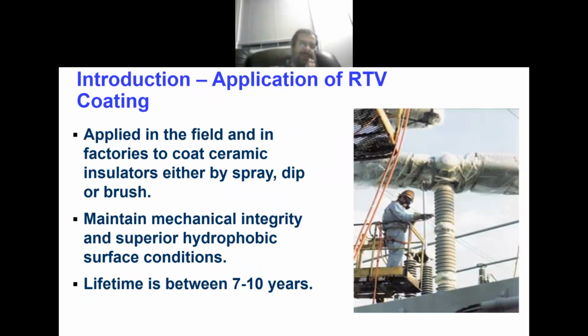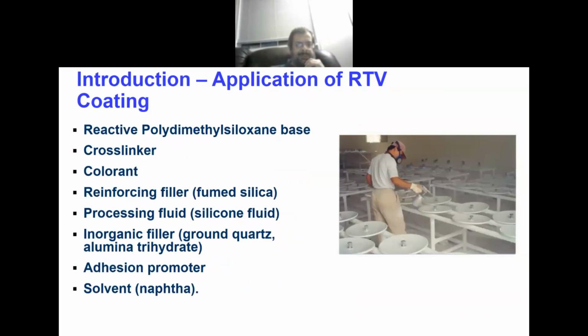Then came the solution of the RTV coating. The RTV coating is basically a room temperature vulcanized coating made from silicone rubber, the same material we used for the non-ceramic insulators we started with. So you come and spray the insulators, and you will have the advantages of a surface with low surface energy, the hydrophobic surface. In many countries, it has been reported that 7 to 10 years is the lifetime, which is very good. The good news here is that for 7 to 10 years, you don't need to wash the insulators. It is maintenance free. So all these costs, for example in some places in Saudi Arabia, you have to wash the insulators every 6 weeks. Imagine the cost involved compared to just going and coating these insulators. This is a big advantage. Next, please.